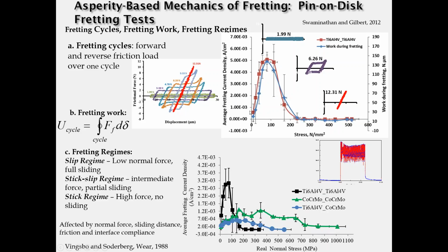And the corresponding fretting currents that you obtain from such a test are shown here, where they correlate very well with the work of fretting. In other words, the more work done, the greater the amount of current generated, and as that work diminishes, as you get more sticking of the interface, you get less fretting. This also points out that there are conditions where high contact stresses will suppress fretting and will essentially shut down the fretting corrosion reaction.